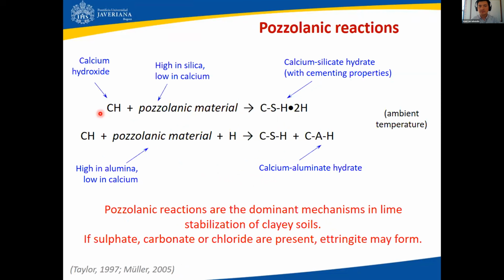And finally, I just wanted to mention pozzolanic reactions. I'm sure you are familiar with them as well. You may remember that when calcium hydroxide combines with a pozzolanic material, which is typically from volcanic origin or calcination, for example, metakaolin, even fly ash has pozzolanic properties. Some fly ashes have pozzolanic properties. Those are materials that are high in silica, but typically low in calcium. They are going to produce at ambient temperature a calcium silicate hydrate. And this material has cementing properties. And that's why pozzolanic materials are interesting and useful, because from a material that does not have cementing properties, with reaction with calcium hydroxide, you get a material with cementing properties.